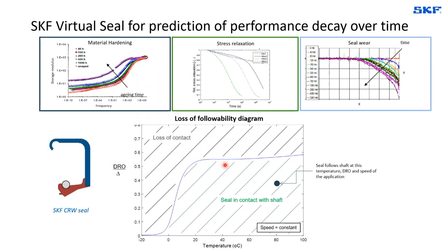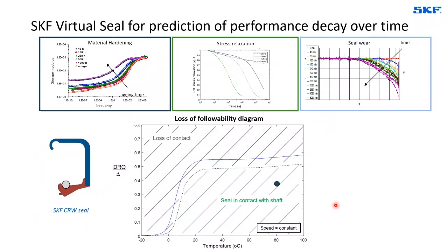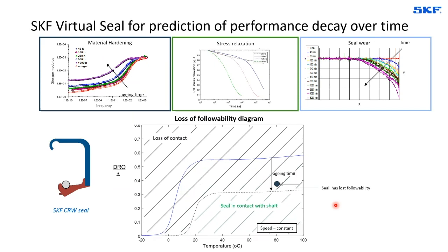If you remember this diagram that we had initially at the beginning, you probably recognize the area below the curve being the area where the seal remains in contact for a certain condition. If this was a working point at the actual temperature of 80 degrees, where the seal would be properly working, as time is passing by, for example at high temperature, for an NBR compound, this area becomes so small that the working point initially in the green area suddenly becomes a failure point, simply because over time the aging has taken place and challenged the seal behavior, and this is now a failing seal in application.